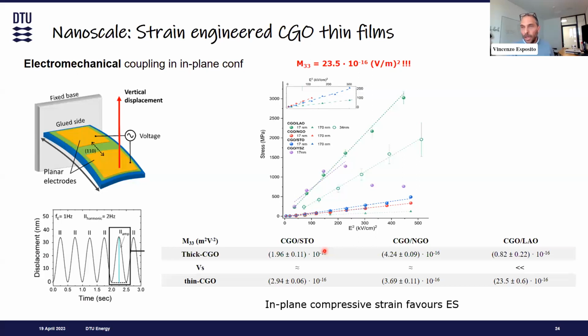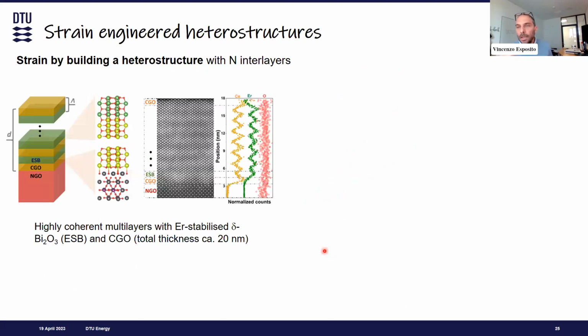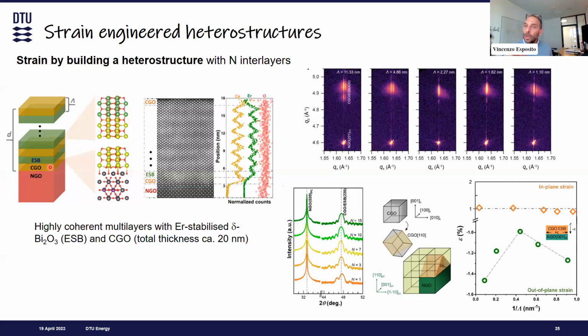Since we like this kind of approach, because it is not only giving interesting experimental results but also defining some new possible mechanism in this material, we have decided to extend the effect of strain in a so-called multilayer heterostructure. In this case, we replicate the number of interfaces that we have between the substrate and the film in the film itself, using different materials that have a slightly different lattice parameter. When we stack them together in a multilayer system, we basically generate a compressive, rather uniform stress in the material that gives a strain to the film. And this is confirmed, of course, through XRD.